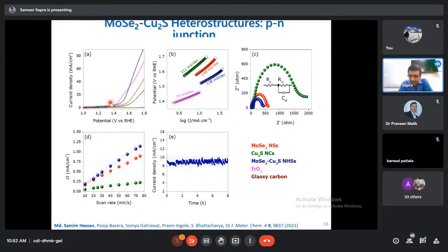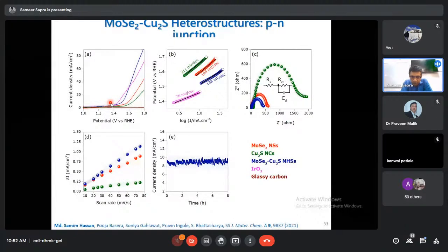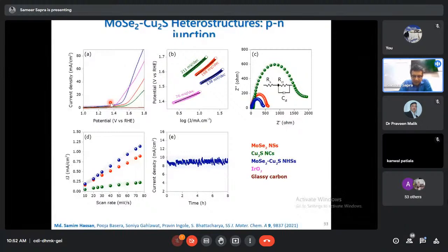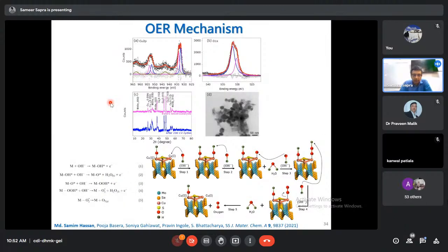And the devices are very stable, by the way. Although this data which was published was for 8 hours, now we have it for more than 24 hours. It's just that the instrument cannot run for so long continuously. But otherwise, they are very stable. And this is the mechanism of the oxygen evolution reaction. And this mechanism we again are able to deduce with the help of some photoemission data.